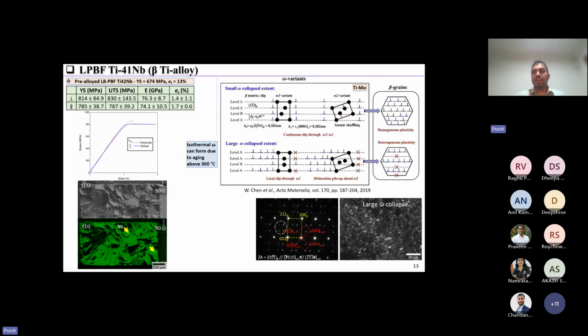So we did some TEM and we saw large omega particles present in this material. Omega phase forms in beta titanium alloys. There are several variants, and two are important. If you have a small omega collapse extent, this is the structure you form, and in this case you can have some homogeneous plasticity. But if you achieve a large omega collapse extent, which usually happens by forming isothermal omega if you age your beta titanium, then because of the structure of this omega phase, you have heterogeneous plasticity.